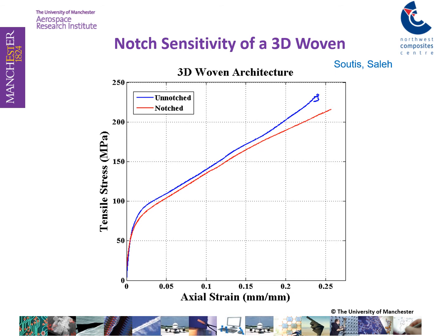And here we compare the stress-strain response of the undamaged laminate and the damaged one with an equivalent open hole. And we can see that the 3D woven construction can function in the presence of the damage, in the presence of the hole. It does not really feel the hole.